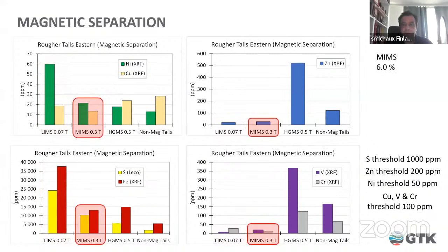So the medium intensity fraction represents 6% of the mass. So if we summed the low and medium together, it'll be about 13% of the mass. And so we're actually reasonably close to getting to the point where we're removing problem metals like nickel and copper, but we're still not quite there. We certainly don't have enough in terms of sulfur.